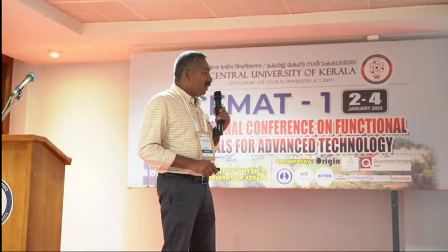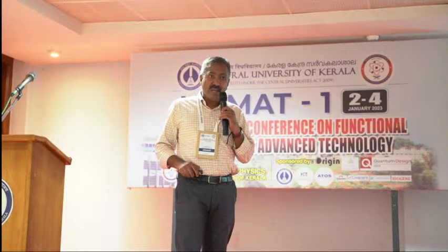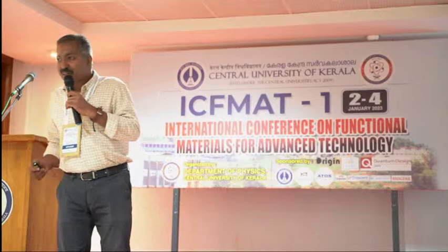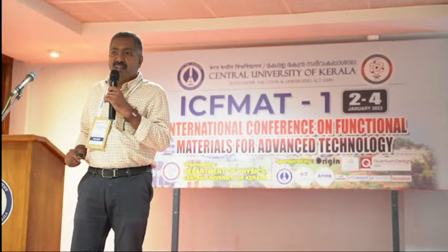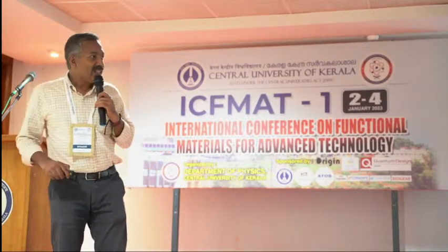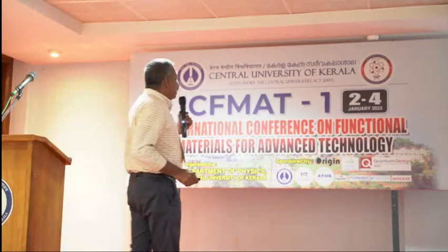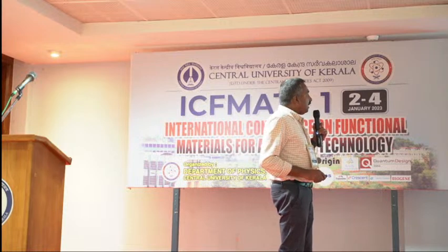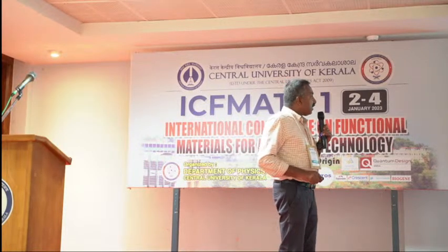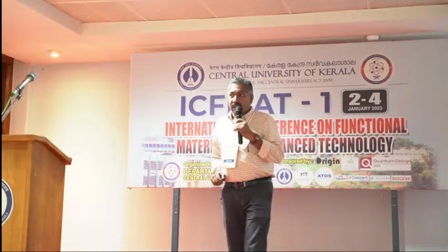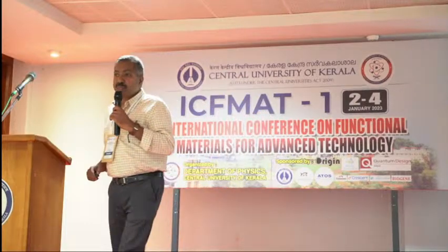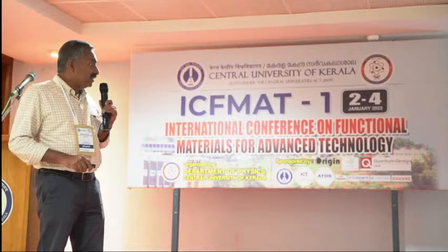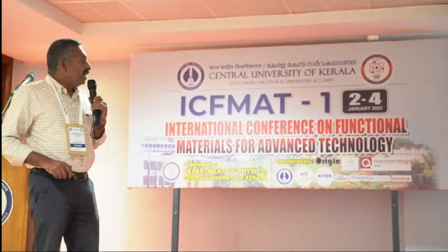So now we are much more into the molecular domain. One can call these metal molecules. I mean, there is no such nomenclature, but this is more or less what it is. And then we could see that if you look at the nonlinear transmission through these materials, the smallest clusters actually behave very much like very good optical limiters. But when you go to the higher clusters, when the size increases, the behavior completely changes.